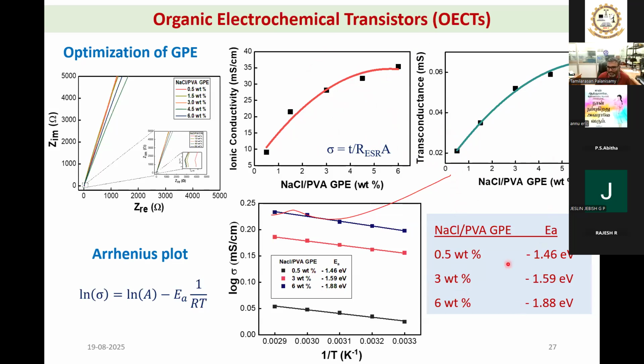If I want to calculate the activation energy, I need to do a temperature dependent study, and we have done it, and we fit those data with an Arrhenius plot. From this fit, we extracted the activation energy, and this activation energy is almost similar, though it looks like it is changing from 1.46 to 1.59 and 1.88. But for this change in weight percentage, this change is pretty minimal. So we can take anything in between. So we have generally taken 3 weight percent NaCl PVA GPE for subsequent studies.